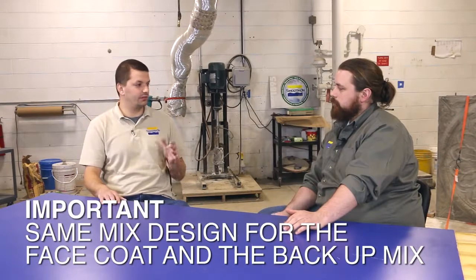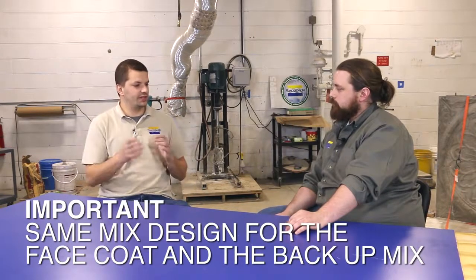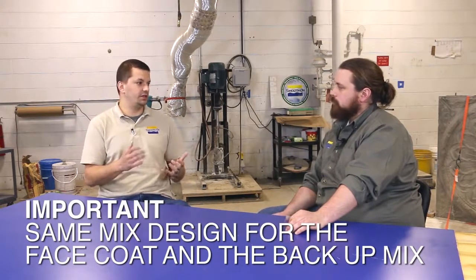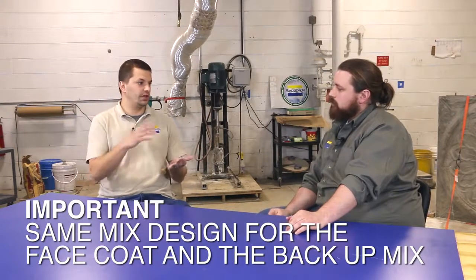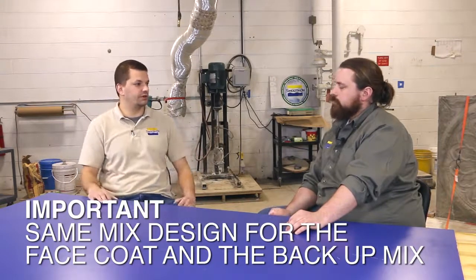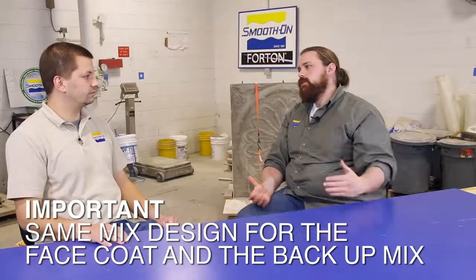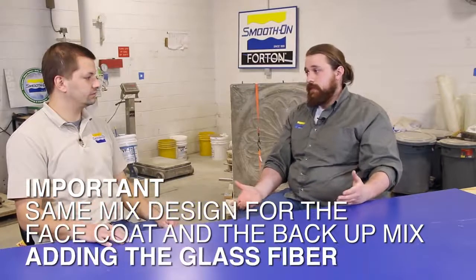Now the backup mix is identical, right? That's the same exact components for the face coat as the backer mix, right? Yeah, having the same mix design is very important. If the mix design is different, it could cause delamination in the ultimate piece between the face coat and the backer mix, which could be catastrophic. So the only difference between the face coat and the backup mix is the addition of the glass fiber.